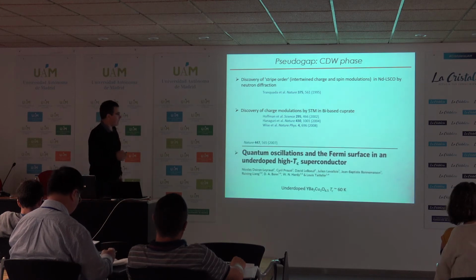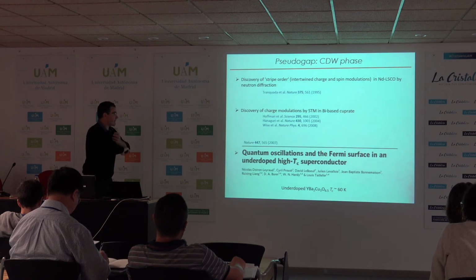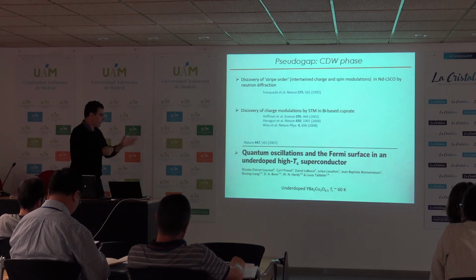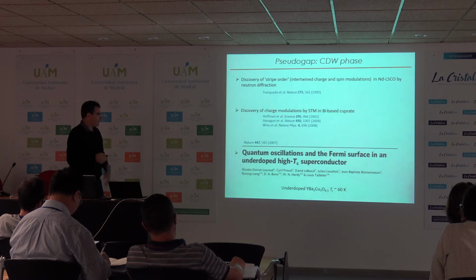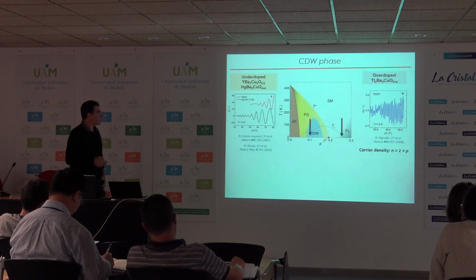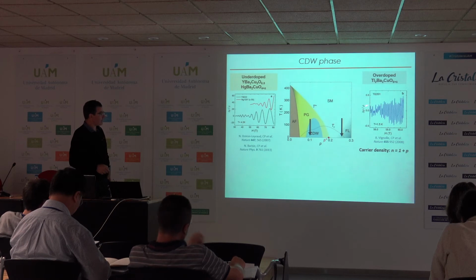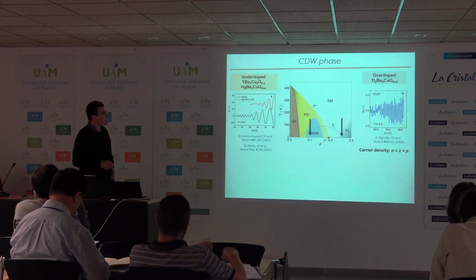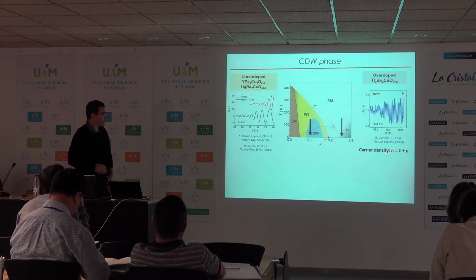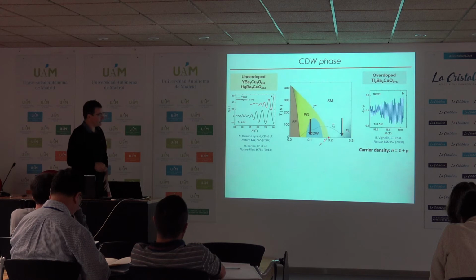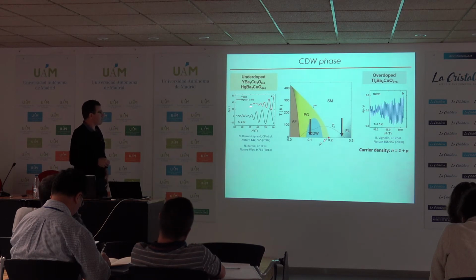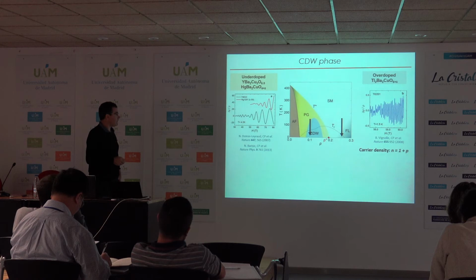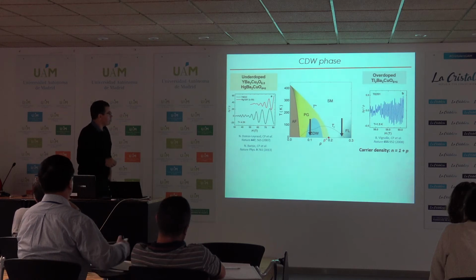And in YBCO, the discovery of charge density wave was triggered by the discovery of quantum oscillations 12 years ago, in my lab in collaboration with Louis Taillefer. Now I will discuss underdoped YBCO, and I would like to start by comparing quantum oscillation measurements on both sides of the phase diagram. I presented before the quantum oscillations in overdoped thallium 2201, with a high frequency of 18 kilotesla and a carrier density of 1 plus p. And here I show you quantum oscillation measurements in YBCO, but also in the one-layer mercury compound, 1201.